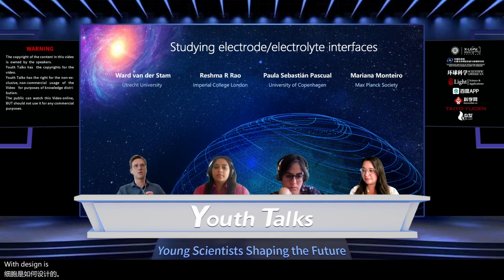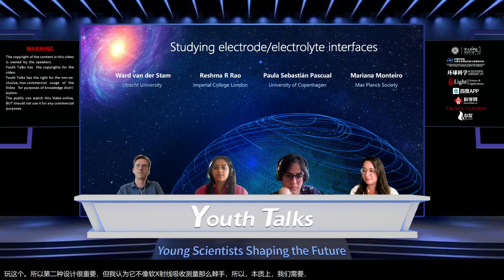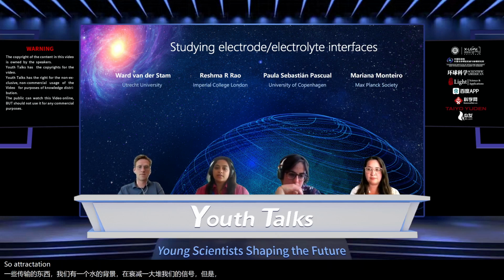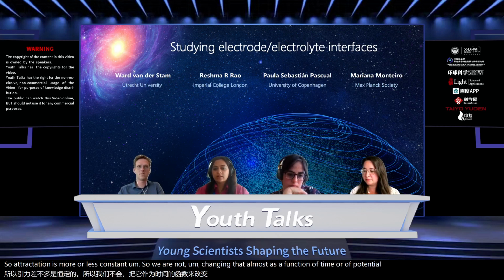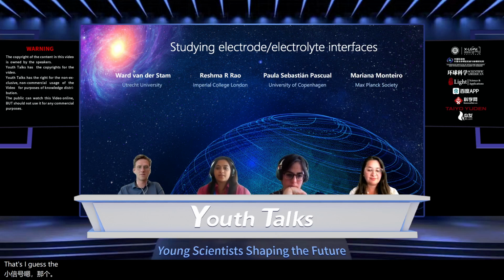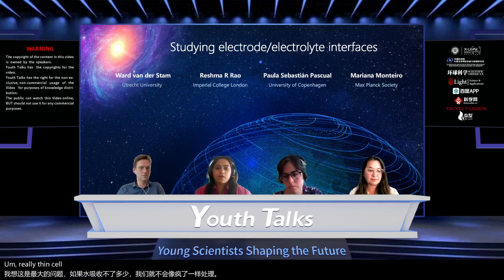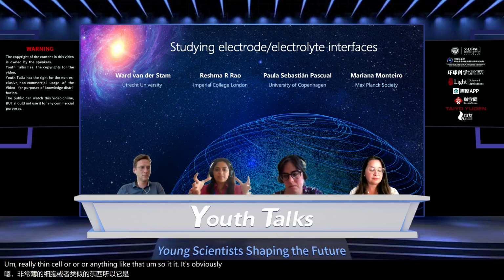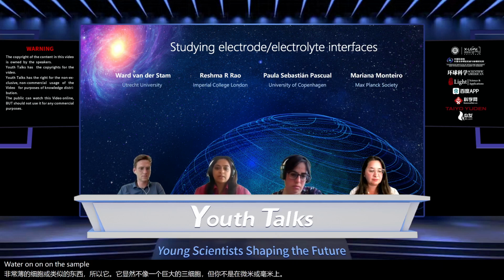So cell design is important, but I think it's not as tricky as, for example, the soft X-ray absorption measurements. Essentially we need something transmissive, and we have a water background. That attenuates a huge bunch of our signal, but that attenuation is more or less constant. We are not changing it as a function of time or potential. So if we just learn to live with that lesser signal, that's, I guess, the biggest issue. And water doesn't absorb a lot, so we're not dealing with crazy, really thin cells or anything like that. It's obviously not a massive 3-electrode cell, but you're not at microns or millimeters of water on the sample. So yeah, I don't know if that answers the question completely. So it's not as tricky.